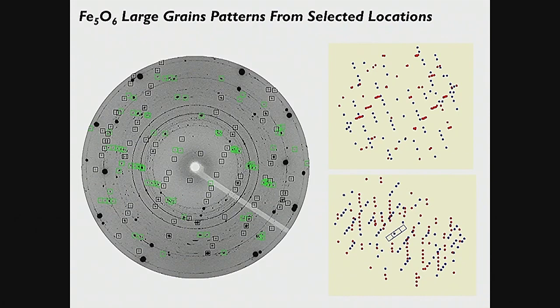And by processing and understanding different grains and different conditions across the sample chamber, I can work out the statistics of those problems affecting crystals that I cannot get rid of. They will not be the same for each crystal. And when I look at different crystals, I understand what becomes a problematic signal and what is a clean signal. And I was able to collect a pattern such as this one.